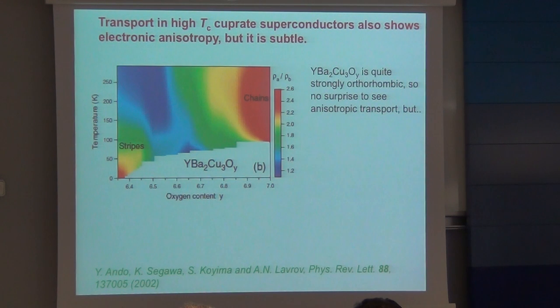Okay, so now we begin with high temperature superconductivity, and let's review a little bit about what happens there. And here the source paper to my taste came from Yoichi Ando's group back in 2002, although there were famous observations of stripe-like ordering in lanthanum strontium copper oxide before that, if you're an expert. But this paper wasn't widely accepted when it first came out, because it seemed to be making a rather roundabout argument. So this high-temperature superconductor has planes of copper and oxygen, but it also has copper-oxygen chains. So it's actually quite a strongly orthorhombic structure.